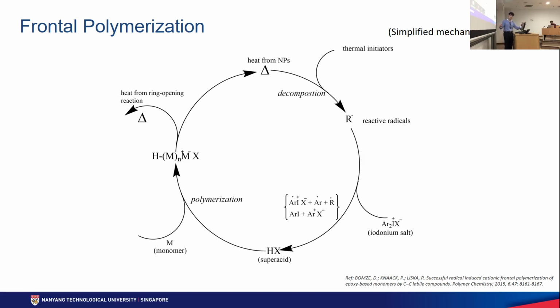And in the process, a byproduct is the heat from the ring opening polymerization reaction. And you can see after we've turned on the AMF and reactions progress, sometimes we'll actually have enough heat for this process to become autocatalytic, because this heat from the ring opening polymerization will continue to decompose the reactive radicals.